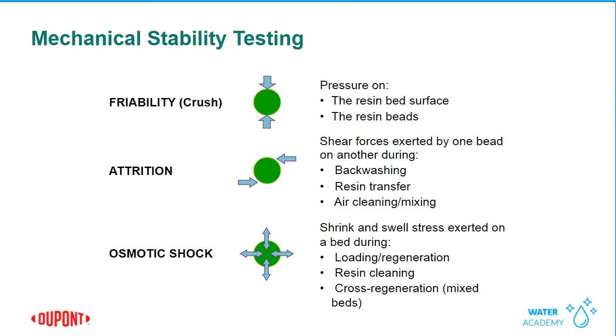To investigate whether a resin is going to be able to withstand the pressures that are exerted on it in the resin bed from delta P, for example, we'll do a friability test where we put single beads under a piston and compress them until the breaking point. That'll measure the force that's needed to break that bead.